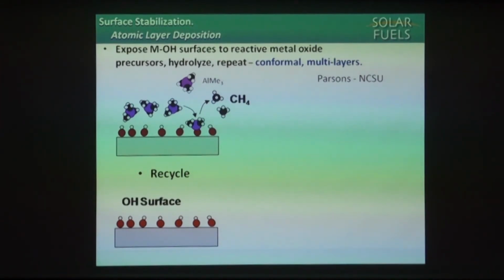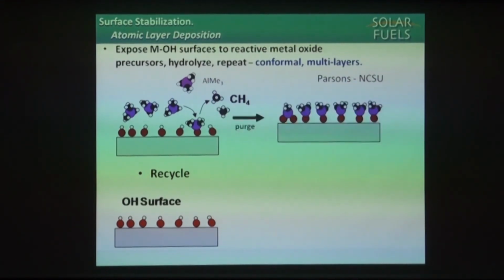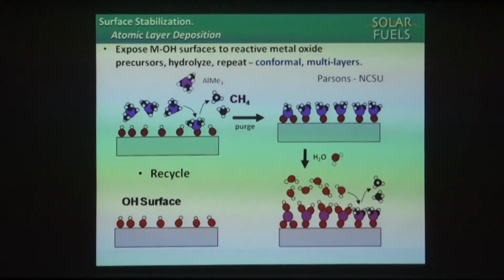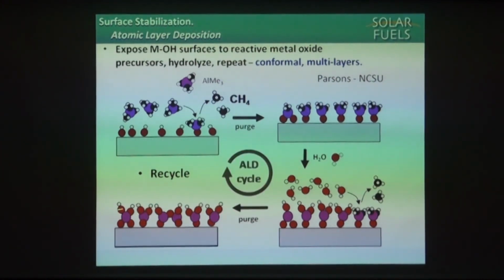In this experiment, you take an oxide surface and a highly reactive precursor to a stable oxide, in this case, trimethyl aluminum. The trimethyl aluminum hits the surface and sticks, and you now have sort of an oxide aluminum, and you still have methyl groups. The next step, you add water and hydrolyze them off to make methane. Next step, you now have the beginnings of an oxide layer. And you can build layer after layer after layer. It's a gas phase technique. It's totally conformal. It goes completely through these films. Great. And then you recycle.